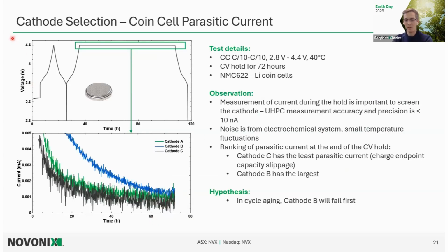We can also do this directly with coin cells instead of using cyclometrics to measure the rate of these slippage-based mechanisms. You can do this directly just by using a constant voltage hold and directly measuring the current required to maintain the cell at that voltage. After a while, all your kinetics go away, your cell is fully charged, and the only current that you're measuring is the current that you're fighting due to all those slippage-based mechanisms that I talked about earlier. And so in this case, just within a couple days of a very long constant voltage hold, we can see this ranking for these different materials.